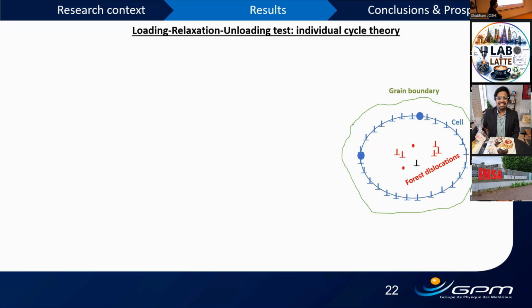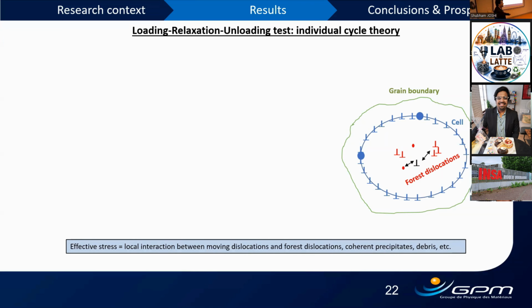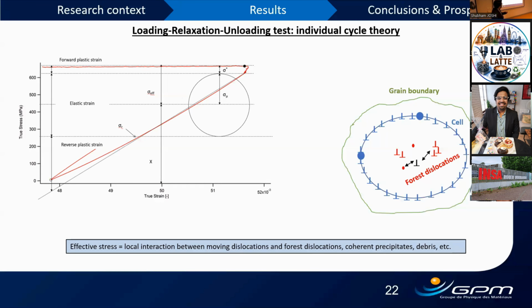Which is sitting in black in the middle of this matrix. Now, if it has external load, it will certainly move. It will have interactions with different microstructural features. If it interacts with short-range interactions like forest dislocations or coherent precipitates, this interaction is classified as effective stress. So we can understand what part of flow stress is coming from which microstructural interaction. Mechanically, we can compute this if we take one sequence. Here only the unloading segment is magnified. Depending upon the position and the radius of this elastic domain, we can mathematically compute the value of effective stress.